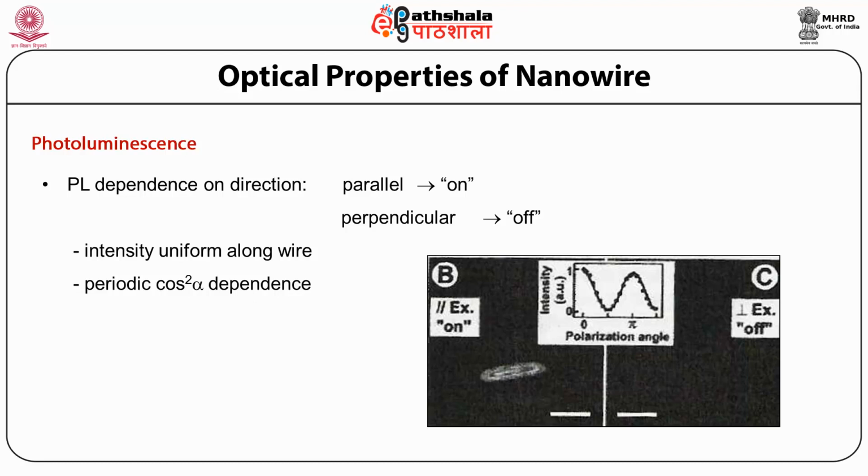The wavelength of light used to probe the sample is usually smaller than the wire length but larger than the wire diameter. Hence, the probe light cannot be focused solely onto the wire, and the substrate on which the wire rests, or the host material if the wires are embedded in a template, is simultaneously probed.